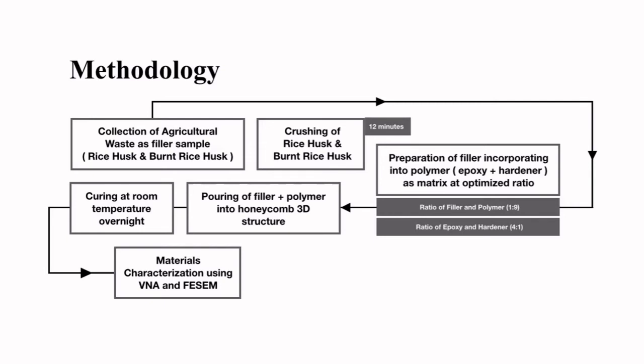For the polymer matrix, we use epoxy resin and hardener at a fixed ratio of 4:1. For the composites, the filler and the polymer ratio is 1:9. Then the composite is poured into the honeycomb 3D structure and cured overnight at room temperature. And the last step, it will be characterized using a vector network analyzer and field emission electron microscope.